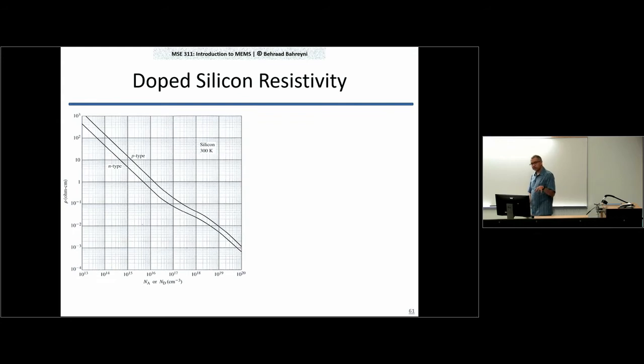So if you look at how the conductivity changes with the dopant concentration, this is a graph. You can see that for p-type dopants, you get slightly higher resistivity than n-type dopants for the same concentration. And the reason is that issue that I mentioned, that holes move a little bit slower than electrons in a lattice, in a silicon lattice. And therefore, you get a little bit higher resistivity for the same number of dopants. But nonetheless, you can reduce the resistivity by increasing the number of dopants.